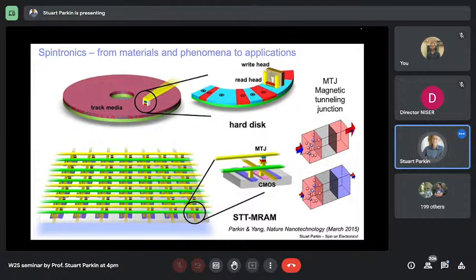And I know these have been probably extensively discussed in the 100 seminars of this series. But just to remind you, a magnetic tunneling junction is essentially the same as a spin valve, except the copper layer is replaced with this gray layer, which is an insulating layer. And in 2004, I showed that, in fact, using magnesium oxide as that tunneling barrier, you could see changes in the resistance of a tunneling junction at room temperature of more than 200%. And this is 20 times that of a spin valve metallic system. And because it's an insulating layer, the resistance is much higher and you get much greater sensitivity.